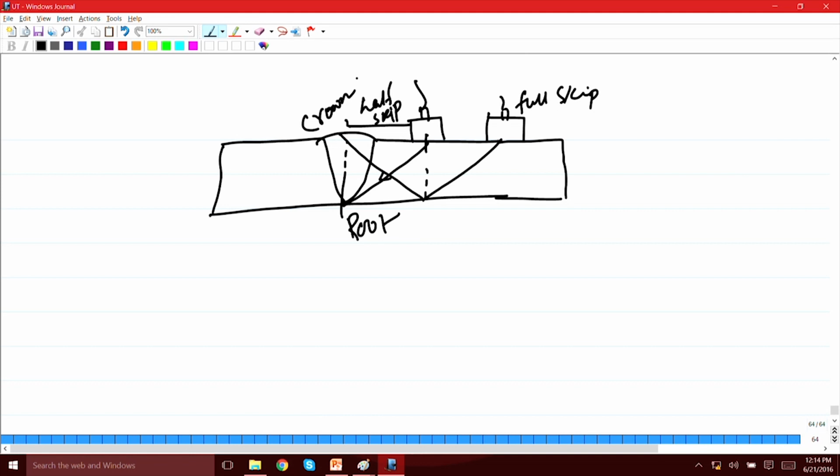you need to move it from half skip to full skip, because as you could see when you move it from half skip to full skip, it is going from bottom all the way to the up. Okay. So, if you are somewhere in between here, then it will go to somewhere in between into the weld, and if there is any defect, then at that defect interface, this will reverse the direction as I said before, and then it will come back to the probe.